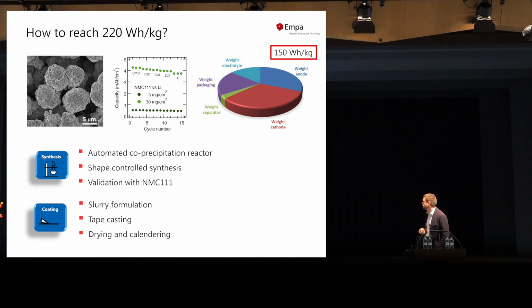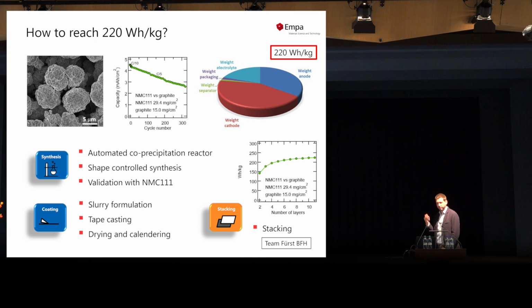And the missing piece is provided by Axel Fürst's group at the Fachhochschule in Burgdorf. Currently we are basically just using one anode and one cathode, so we need to stack several of these electrodes on top of each other to amortize the weight of the packaging and increase the energy density. This is a projection that we did with the same values that we have in our lab cells. You can see if you go up to 11 layers of stacks, we can reach an energy density of about 220 watt-hours per kilogram. So this cell is not yet a reality, but we are working in that direction.